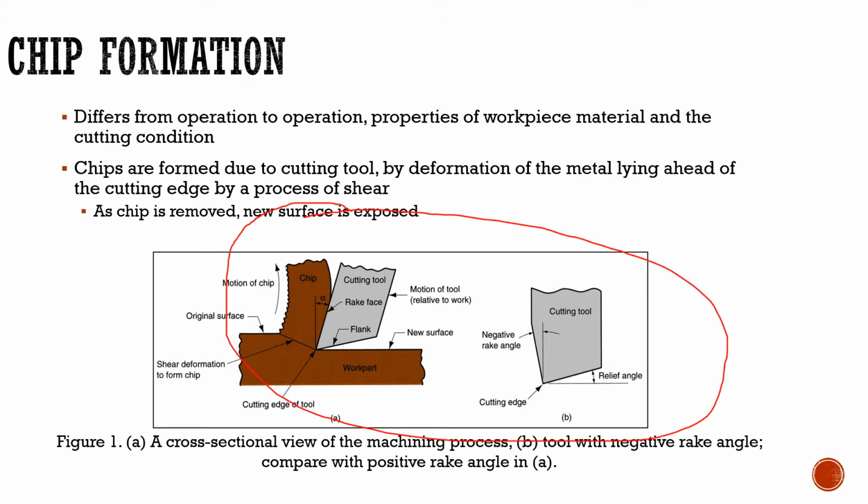A very large amount of strain actually takes place in these regions in a very short interval of time, and not all metals and alloys can withstand this strain without fracture. So gray cast iron chips, for example, are always fragmented, and the chips of more ductile materials may be produced as segments, particularly at very low cutting speed.